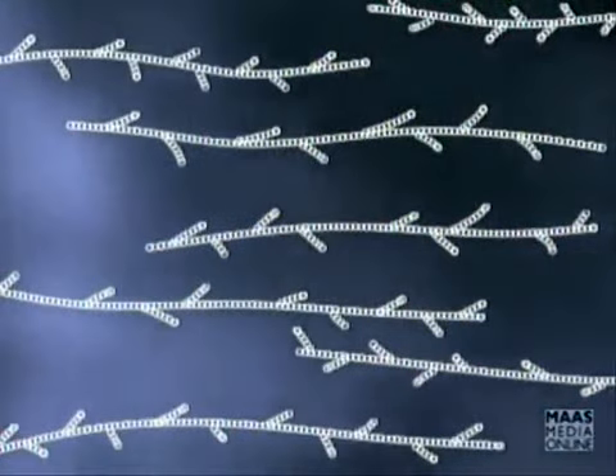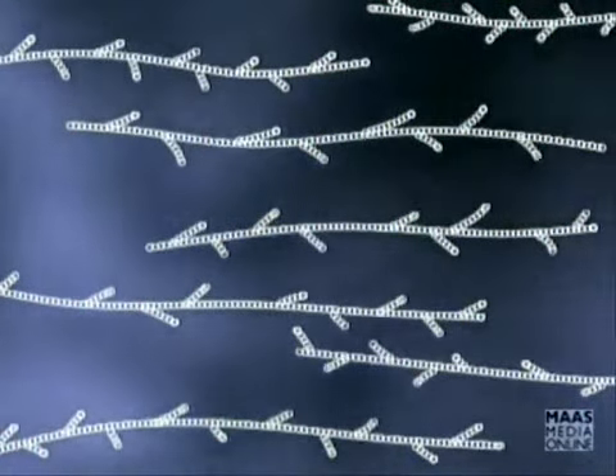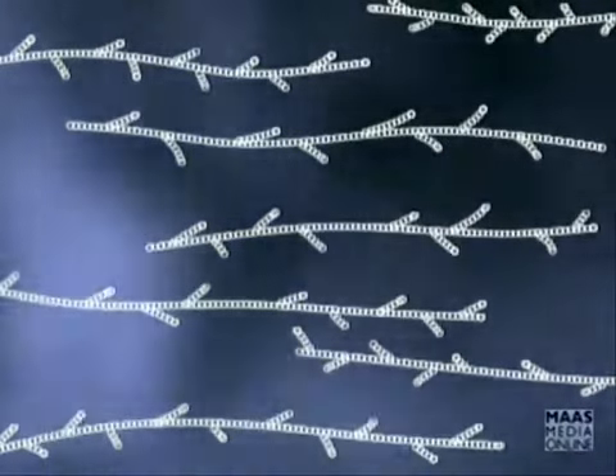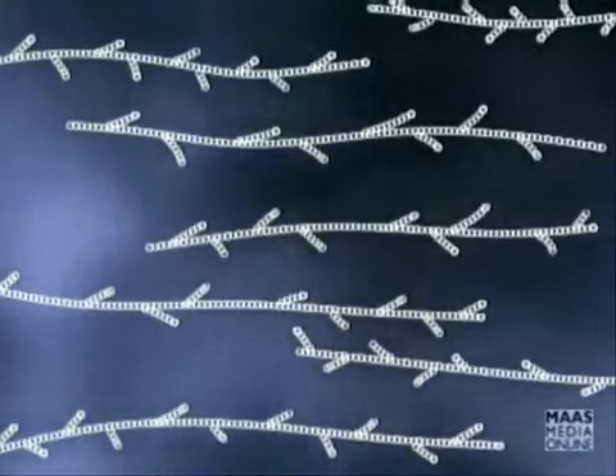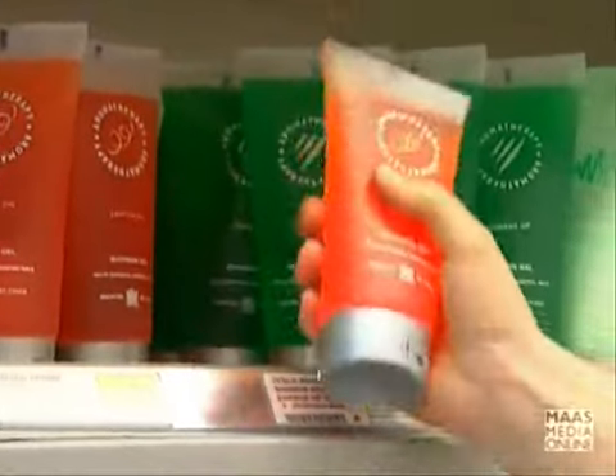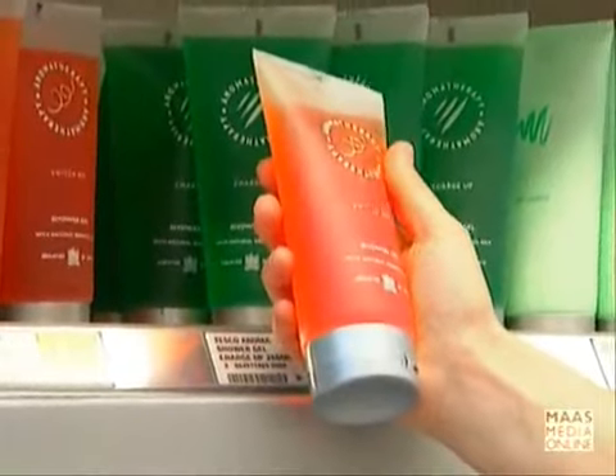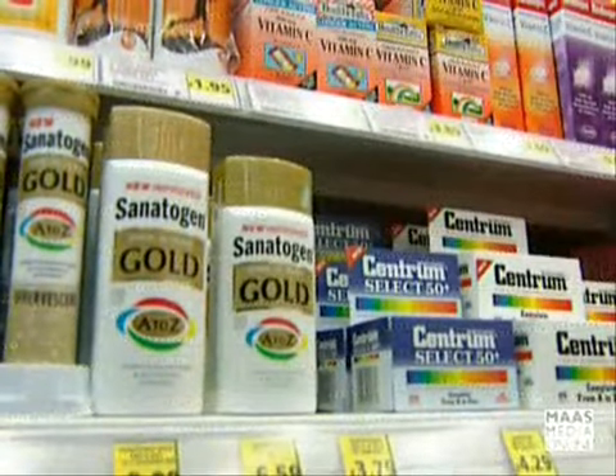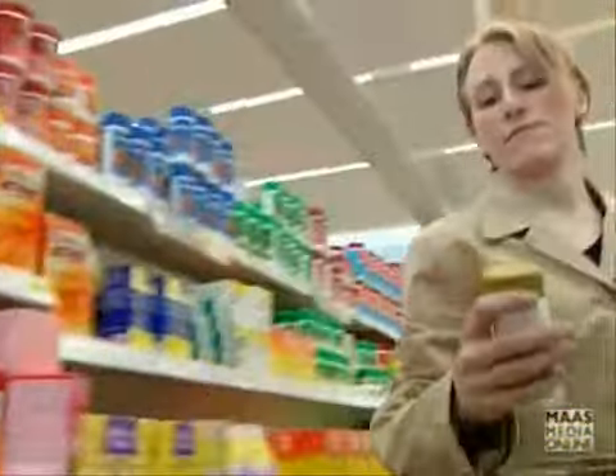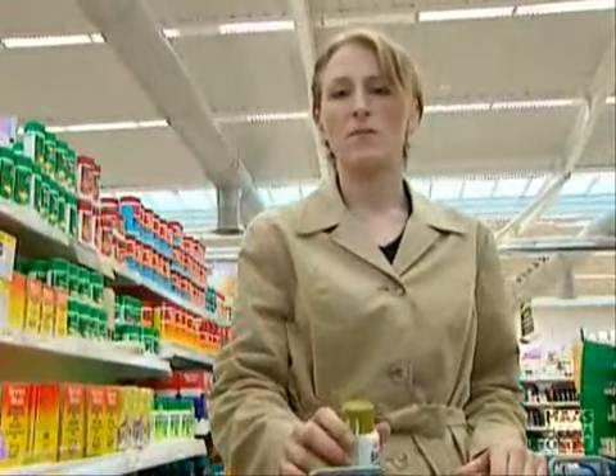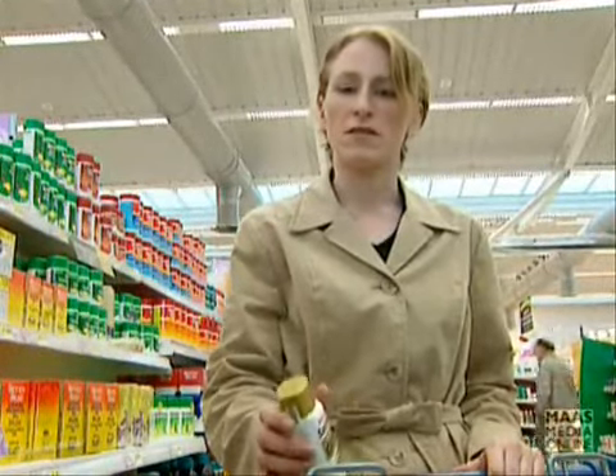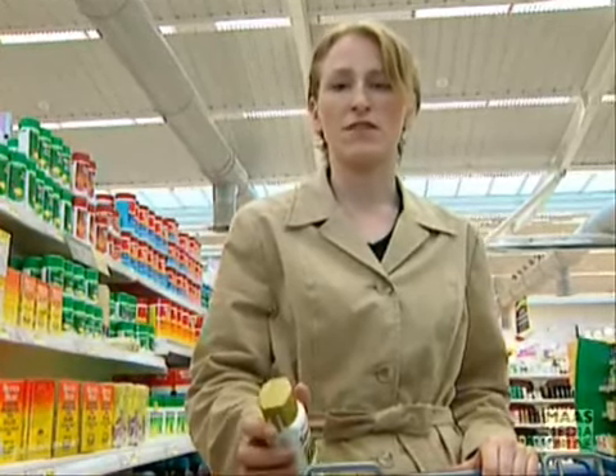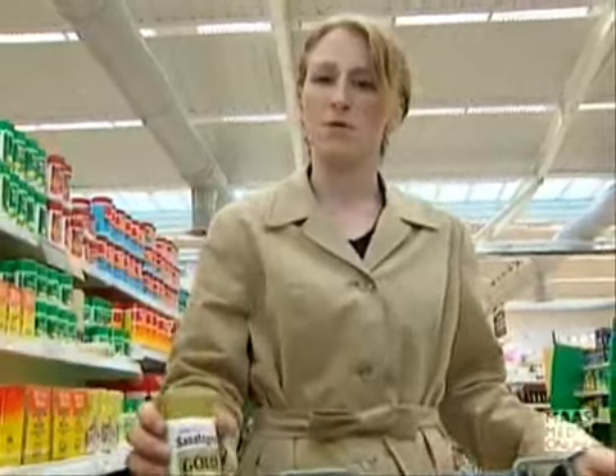In contrast, linear low density polythene, LLDPE, has regular short chain branches. Being symmetrical, they can pack together more easily and give rise to small crystallites, making the plastic stronger and more tear resistant than low density polythene. High density polythene, HDPE, has minimal branching and therefore it's highly crystalline. It's less flexible but more durable and widely used in commercial products. So, even with an apparently simple molecule like polythene, the properties can vary dramatically by controlling the degree of crystallinity. But obviously things can get a lot more complicated than that.